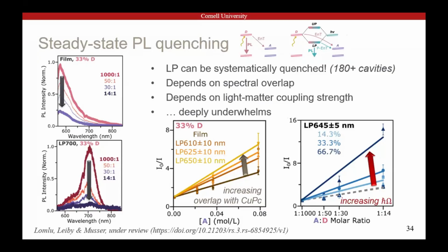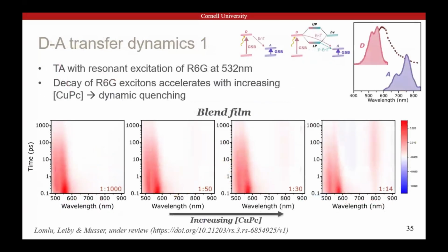Surely its Förster radius should be more than 50% larger than the bare film. What's going on? Fortunately, Rana recognized that if the polariton is able to do something, it's doing it against a very fast clock, because as soon as the polariton forms, it wants to decay as a photon almost immediately, because these are very lossy cavities. They've got 10 femtoseconds to do something. So maybe it is remarkable, but we need time-resolved experiments to understand.